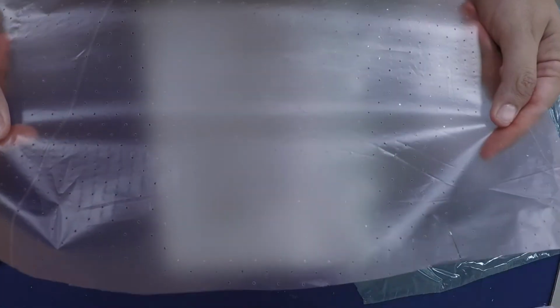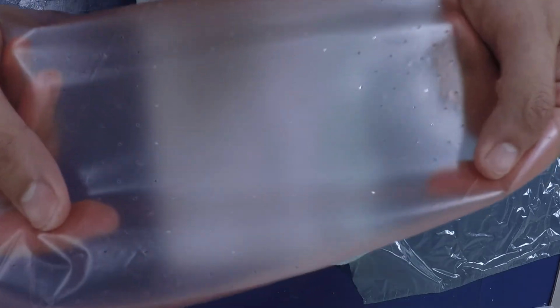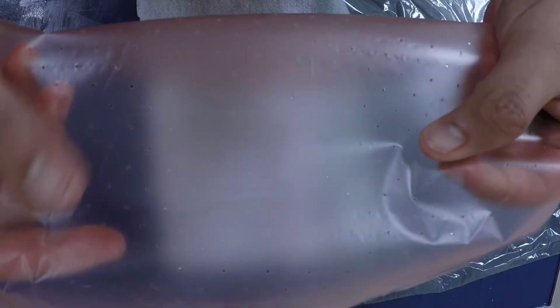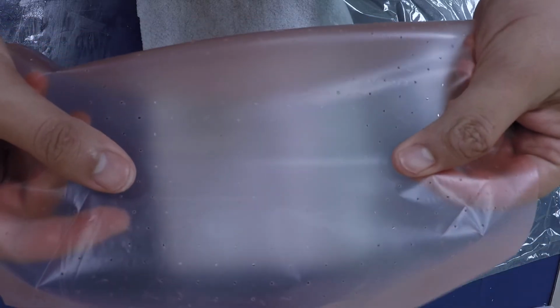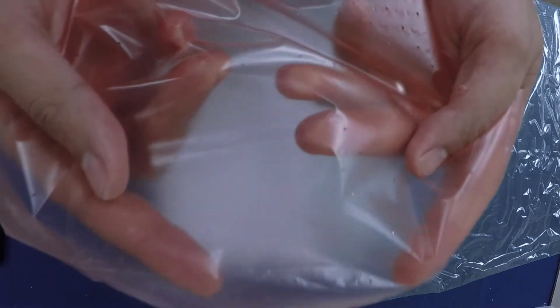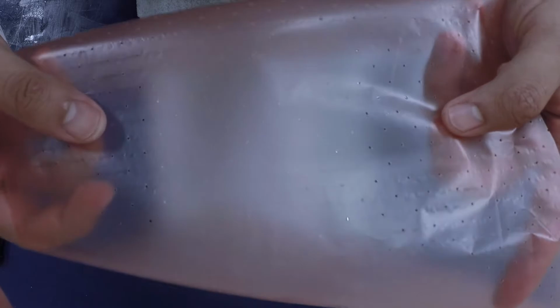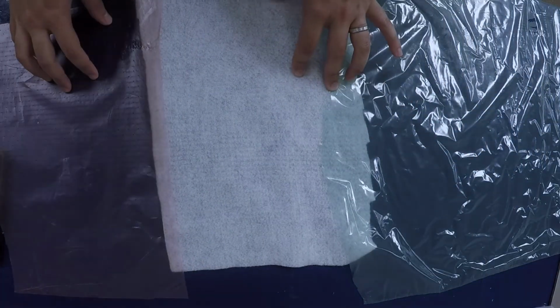The first material is called a release film. The release film is a thin film that is engineered to prevent it from bonding with the epoxy. This film is usually capable of transporting epoxy and air through the film into the bleeder. In our case, our release film is covered with many little holes and it is referred to as a perforated film. There are other types of release films depending on how much epoxy you want to flow through or the finish that you want your final product to have.